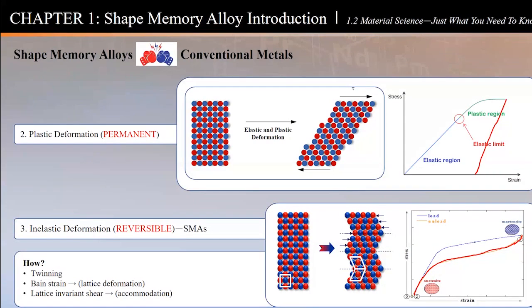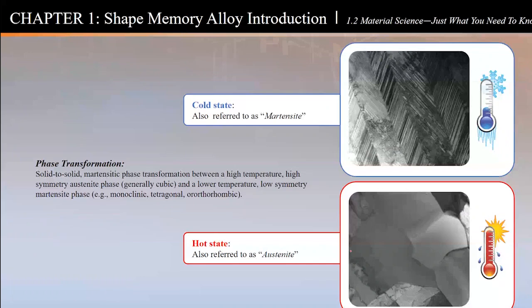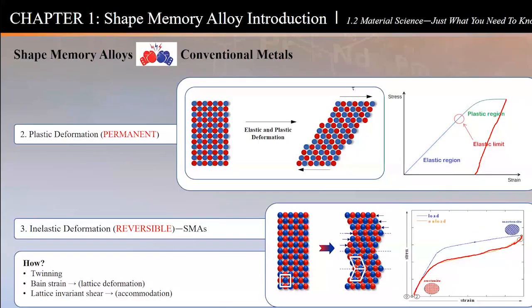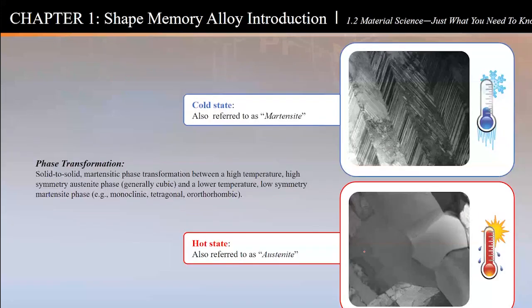So if we go in a microscope and look at the cold state in the lower symmetry, the martensite phase, what's referred to as the martensite, here are those little ridges that I just showed you. You can see how they're going back and forth. This is actually a real microstructure. It looks like this. This is how it accommodates that deformation. You don't break a plane, they just go into this twin modes that you see here.